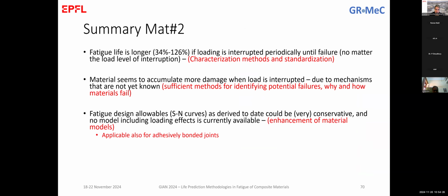So to summarize this material number 2, as we call it, we've seen a lot of increase of the lifetime when we interrupt the loading periodically. This increase, in some cases, you remember this 2 hours creep load interruption. So even if we interrupt the load at the high stress level, sometimes we have increases because of this. And this is a kind of trigger to make us question the characterization methods and the standardization. Because imagine now that you are analyzing materials for a structure, and you want to investigate the material behavior to get material properties to use for your design.